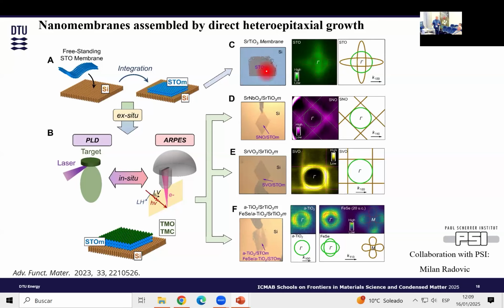Then we took the STO and put it into the chamber again, where there is a PLD coupled to the ARPES, and we deposited the following materials: strontium niobate, strontium vanadate, and iron selenide, which is a superconductor. What we observe is that we got the electronic structure of the material. We didn't look at the properties, I must say. We only looked at the electronic structure while the materials were inside the chamber under the same conditions. And what we saw is that the material behaves as well as if you grow it directly on a single crystal of strontium titanate, which is interesting. In some cases, it was even better.